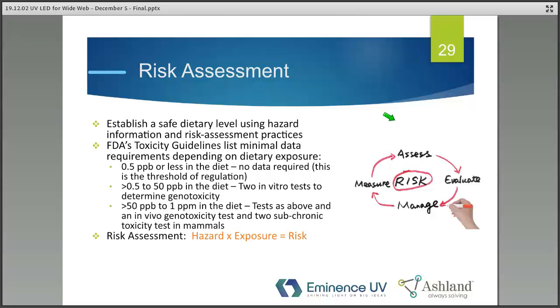Then in FDA's toxicology guidelines, there's a list of the minimum data required. So if you have something that migrates really low at 0.5 parts per billion or less, you don't have any data at all that's required, as long as it's not genotoxic. From 0.5 to 50 parts per billion, you would have to have 2 in vitro genotoxicity tests. And at 50 parts per billion to 1 part per million, you'd have to have the genotoxicity tests and 2 subchronic tests, which are 2 90-day tests in mammals. Those are quite expensive to run, so if it's not publicly available, it could be very expensive to do this.